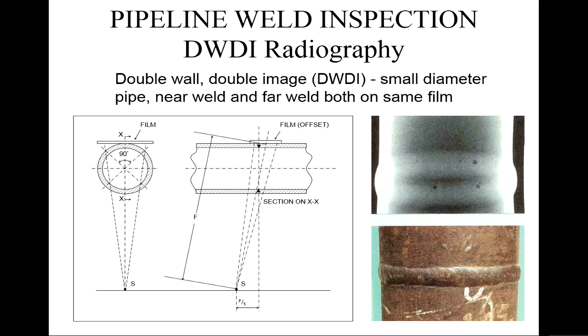So here's that double wall, double image situation with the offset film we've seen before. The X-ray source has some slits in it, which will dictate which direction the X-ray beam actually goes. So we see this angle of X-rays here. That's defined by basically having a hole which those X-rays come out of. So you surround the X-ray source with an absorbing steel box with a small hole in it, and then a bit further out, you have another slightly larger small hole that defines the cone angle. So by controlling the absorption of X-rays before it gets to the pipe, you can control the beam of X-rays that's coming through, and then you can use that to look at different parts of the system.